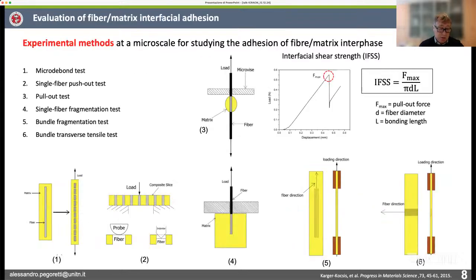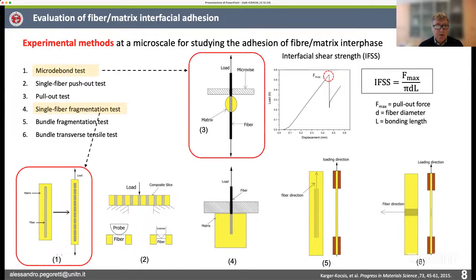In terms of experimental methods, it is quite interesting to observe that over the years, a number of different testing methods have been developed. The most rigorous are based on single fibers embedded in polymer matrices or in metallic or ceramic matrices, but mostly polymeric matrices. Some tests also involve the use of bundles of fibers, but the main ones, if you browse the literature, are actually these two: the micro debond test, which is also widely used here in Trento. We have developed a facility to test our combinations of fiber and matrices according to this technique, and the single fiber fragmentation test, which is also possible to perform here in our laboratories.